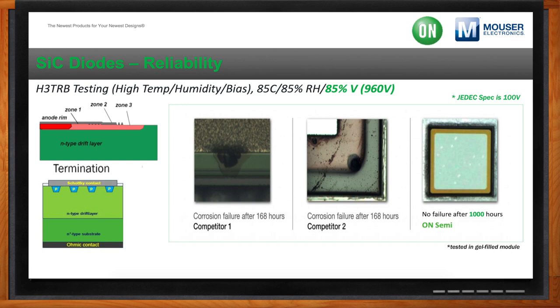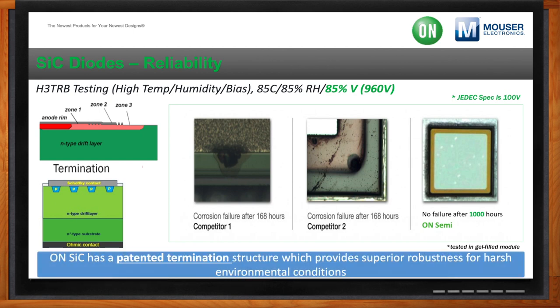Now, JEDEC, for example, is spec to hold that at a constant 100 volts for silicon, but for silicon carbide, we wanted to stress it even higher. And what we found is that when we stressed it at a much higher voltage, we did not fail while other people failed. And in turn, this comes from a patented termination structure, which provides superior robustness for harsh environment conditions.